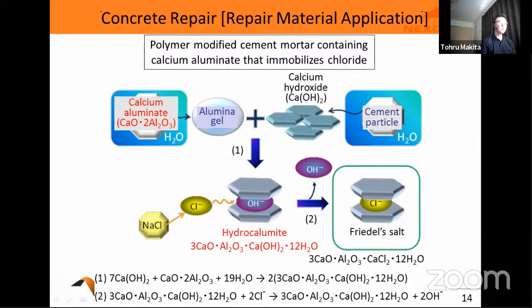So we use polymer modified cement mortar containing calcium aluminate that is capable of immobilizing chlorides and densifying the microstructure of repair mortar. These are chemical formulas showing how calcium aluminate immobilizes chloride. In the next slide, I show you how it works using animation.